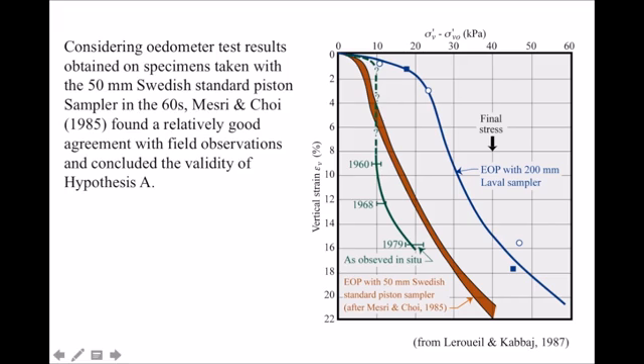For that, they used compression curves obtained on 50 millimeter specimens taken with a 50 millimeter Swedish standard piston sampler. And these specimens were taken in the 60s. And here you have the field curve, and in orange you have a compression curve used by Mesri and Choi. And indeed, the two curves are not very different, which explains why they came to the conclusion that hypothesis A was correct.